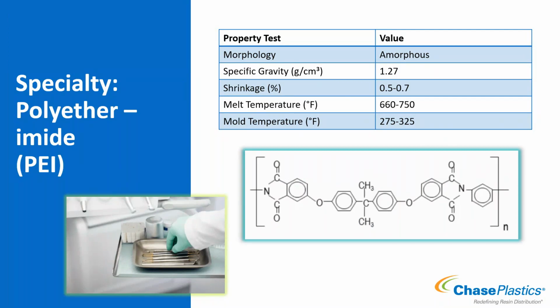Specific gravity of 1.27, low shrinkage. Again, it's an amorphous resin, so 0.5 to 0.7%, and still high temperatures as well. Melt temperatures in the 700 range, just like PEEK, so we're getting into high temperature performance. Mold temperatures around 300 degrees F.